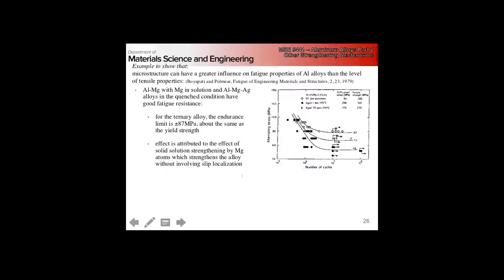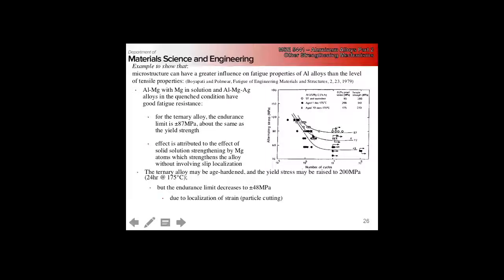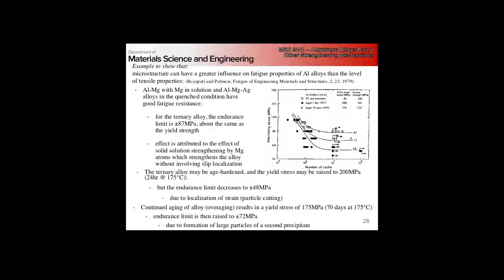we can see that the aluminum magnesium silver, the endurance limit is about 87 MPa. If we then age it, we reduce our endurance limit by almost a factor of 2, because now we've made bigger particles that we can cut due to particle shearing. And then if we continue to age them, if we overage them, it goes back up, because now we have big particles that aren't going to localize the slip anymore, now that we're going to loop around them. So it's all a matter of degrees here.